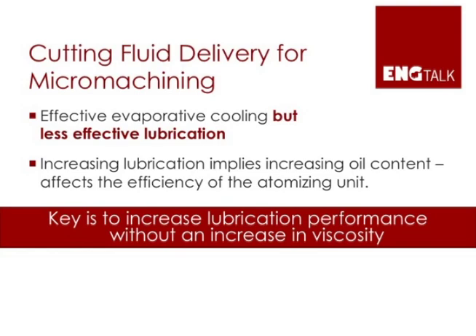Increasing the oil content has a detrimental impact on the performance of the atomizer. If you add more oil into the cutting fluid, the atomizer is not going to be able to pump out tiny droplets. So the key is to increase the lubrication performance of the cutting fluid without increasing its viscosity, and the way we are trying to do this is by the use of nano-scale additives.